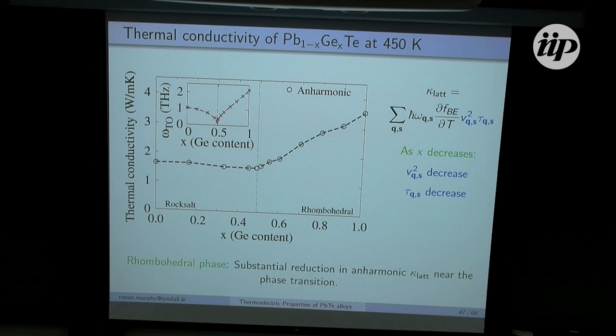Now if we take a look at what happens to the rhombohedral phase, we don't have this as such. So if we start in germanium telluride at 1, we increase the lead content, pushing it closer to the phase transition. Now in this case, as I've shown you again, the phonon lifetimes reduce as we do this, but because our mass is getting heavier, our group velocities are decreasing as well as the phonon lifetimes, leading to maybe about a factor of 2 reduction in the thermoconductivity comparing germanium telluride to, say, this point at the phase transition. So we see that this mass difference in the alloy is definitely impacting how well we can see this minimum value here at the phase transition.